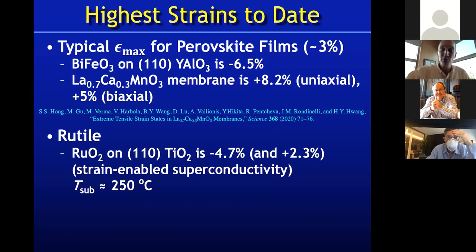The first one is a rutile. It again involves octahedra. I'll show you the crystal structure in just a second. But in terms of strain engineering, the amount of strain in the system is a compressive strain of almost 5% in one direction. It's a huge strain. And you might go, well, how is that possible? Let me point out the quite low substrate temperature. If you're used to making perovskite oxides, typical substrate temperatures might be 700 degrees C. These rutiles have an advantage in that they can be grown at much lower temperatures. So let's have a look at the data.